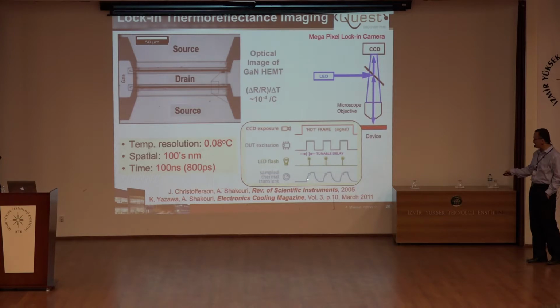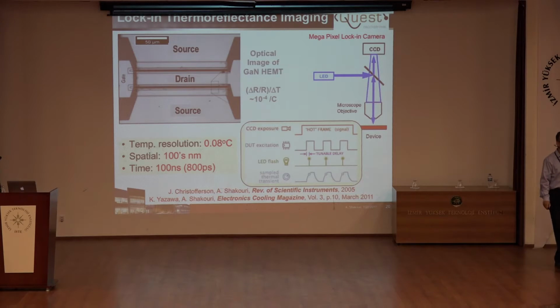Here is the temperature of the device: heats up, cools down, heats up, cools down. And with this pulse of light, I can measure reflection at this point. If I do it precisely, I can measure temperature to below 0.1 degrees. It is a visible wavelength, so I can go down to hundreds of nanometers spatial resolution, and with LEDs or lasers, I can do this stroboscopic measurement down to sub-nanoseconds. So I can really measure temperature very fast at the smallest scale.